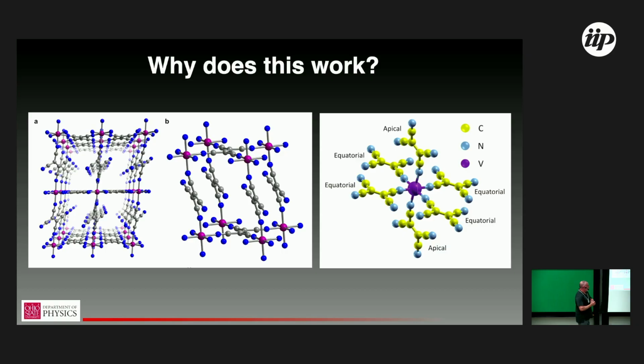I, in the end, didn't drop any slides in, but for fans of the genre, our first paper was a spin LED measurement where you use VTCNE as an electrical spin injector into a light emitting diode and use the polarization of the light to measure the spin polarization. And we got that to work surprisingly in this molecular-based system, which shouldn't really be magnetic, at a heterointerface that should have been much harder to engineer, yet still somehow functioned.